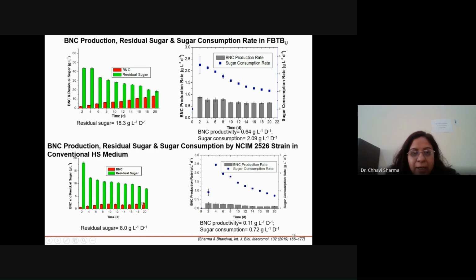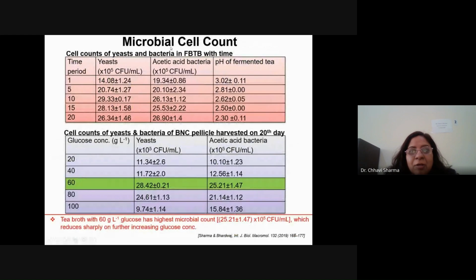And then we also evaluated the BNC production using the conventional NCIM 2526 Acetobacter strain and the conventional HS media. Here, although the residual sugar was only 8 gram, the productivity was only 0.1 gram per liter per day. The reason for the low residual sugar here is that some byproducts have been formed in the media, like gluconic acid, which was later detected by HPLC. We also calculated the microbial count from the BNC pellicle as well as from the black tea broth medium, and found that it contains yeast and acetic acid bacteria at different concentrations.